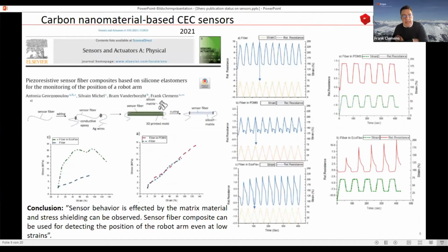So therefore, we thought, okay, let us make an experiment and let us see what's happening if we use two different silicone materials. So here is again a PDMS material, here is an Ecoflex material, and the structure is the same. We made the sensor composites by simply casting. And the interesting part is that you can see here the fiber, and the fiber has really the highest resistivity when we have the highest strain. And when we put in the silicone material, you can see, as I already mentioned, the secondary peak. Interestingly, if we use this Ecoflex material, we have a completely reverse behavior. So you see that the fiber, which is still the same fiber, tends to have completely different sensor behavior. That means now instead of the maximum resistivity, we get the minimum resistivity at the highest strain.